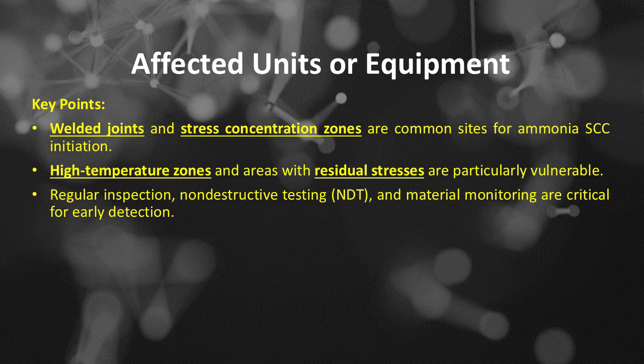Key points: welded joints and stress concentration zones are common sites for ammonia SCC initiation. High temperature zones and areas with residual stresses are particularly vulnerable. Regular inspection, non-destructive testing (NDT), and material monitoring are critical for early detection.